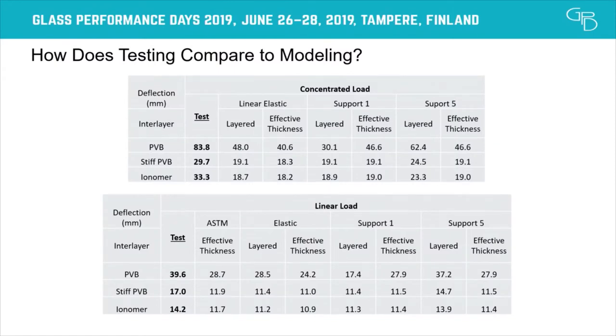So for the concentrated load, the stiff interlayers were okay, not too bad, 10 millimeters or so away. But for the softer PVB, not so much. However, for the linear load, it was a different story. The stiff interlayers were much closer, 3 to 6 millimeters difference. I only measured the deflection because the lab didn't have any strain gauges to measure the stress, so we didn't do any stress, just deflection. But for PVB, it did a little better too. It was 10 millimeters or so, even 2 millimeters in one case.